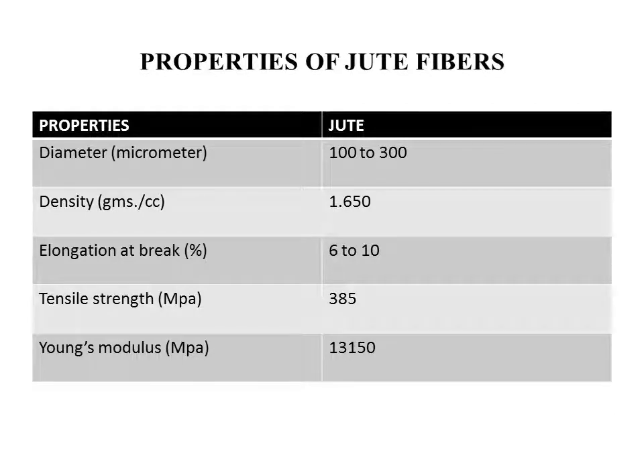Jute fiber diameter is 100 to 300 micrometer and density is 1.650 grams per cc. Elongation percentage at break is 6 to 10. Tensile strength is 385 megapascal and Young's modulus is 13150 megapascal. Compared to the flax fibers, the jute has a lower Young's modulus value.